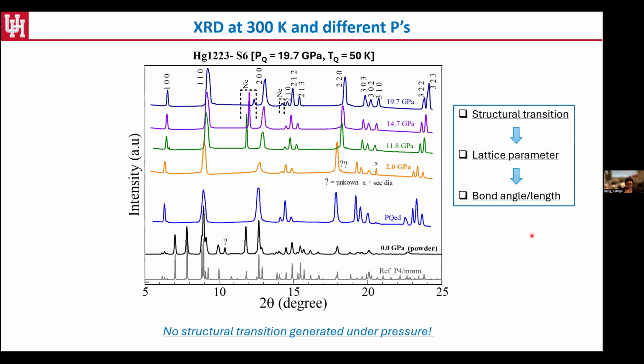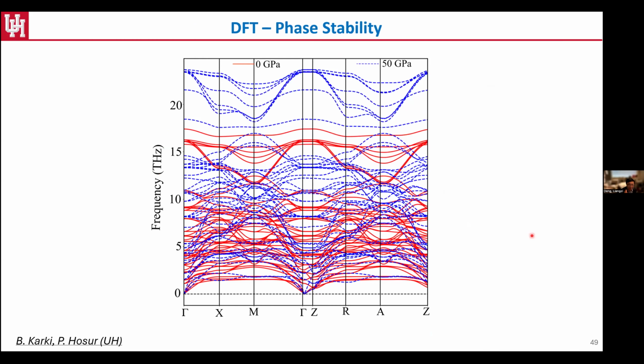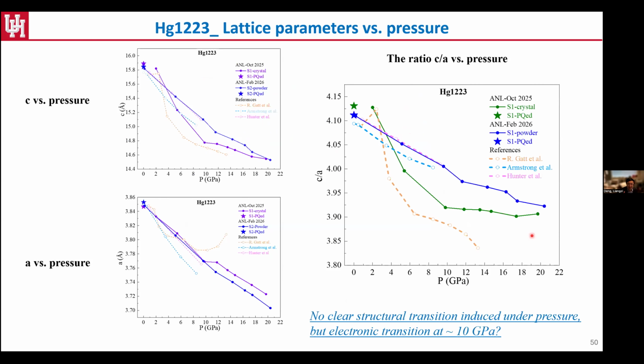Then we moved on to the next parameter. We know that even though no structural transition occurs, the lattice parameter must be changing under pressure, but whether we're retaining those lattice parameters is another matter. We also have DFT calculations proving that the phase was pretty stable all the way up to 50 GPa. Since we didn't observe any structural transitions, we moved on to the lattice parameters. Those two stars, the blue star and the green star, show the lattice parameter after pressure quench, and again, it's very close to the ambient, pristine sample. So that means we cannot say it's because we're retaining the lattice parameter that was created under pressure.